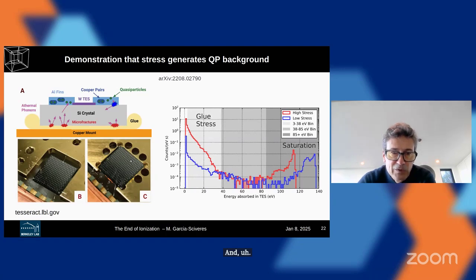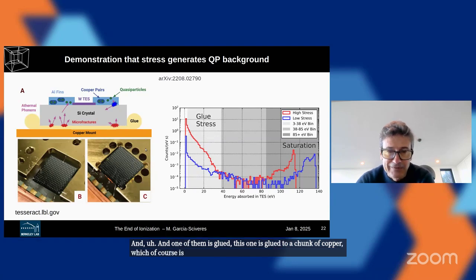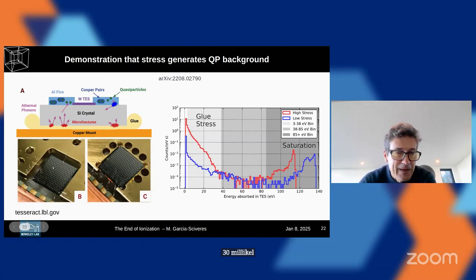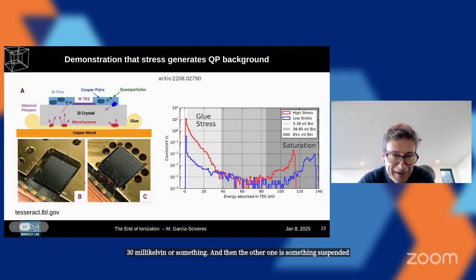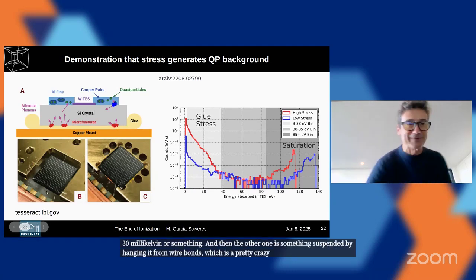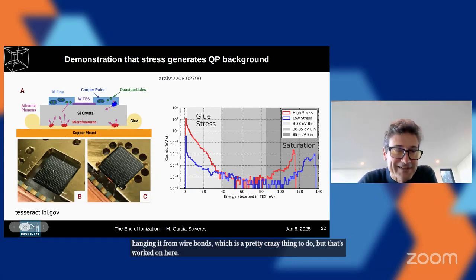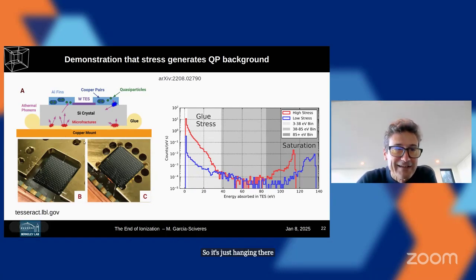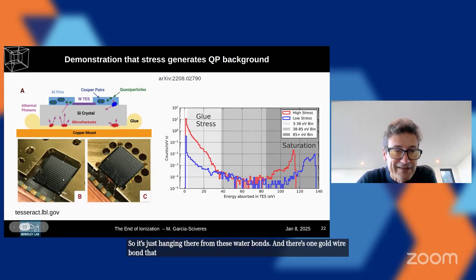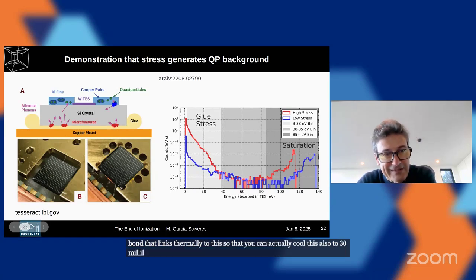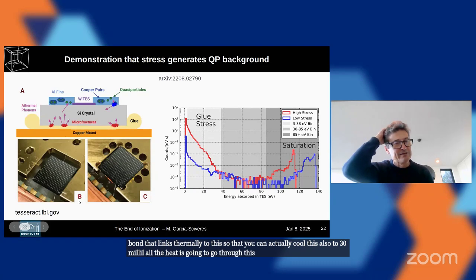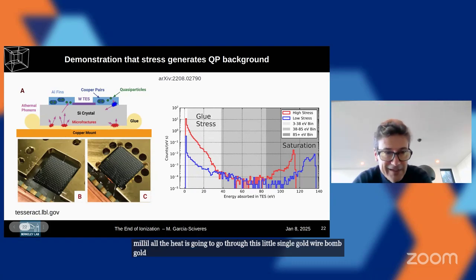And one of them is glued to a chunk of copper, which of course is how you cool it. This has to go to 30 millikelvin or something. And then the other one is suspended by hanging it from wire bonds, which is a pretty crazy thing to do, but that's what's done here. So it's just hanging there from these wire bonds. And there's one gold wire bond that links thermally this to this, so that you can actually cool this also to 30 millikelvin. All the heat is going to go through this little single gold wire bond. Gold is a very good heat conductor at low temperature.